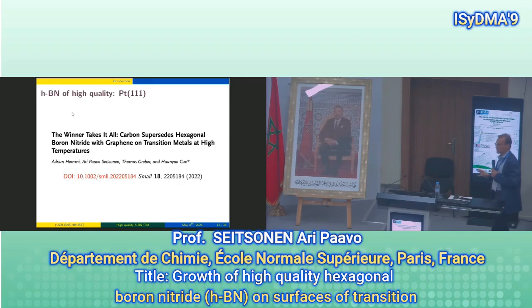Then the second example I want to show about the growth is now hBN growing on platinum-111, a different substrate. It has different interaction strength, different lattice constant, and we wanted to look at how this affects the growth of hBN. One has to remember there's usually also carbon dissolved into the bulk of the transition metal. So here one has to be careful. Then one has not only boron and nitrogen, but often there's also carbon which comes from the substrate if the substrate was not very or ultra clean before the experiment.